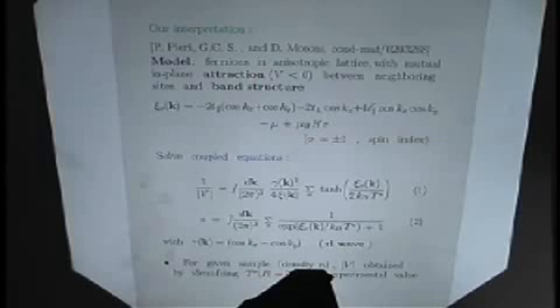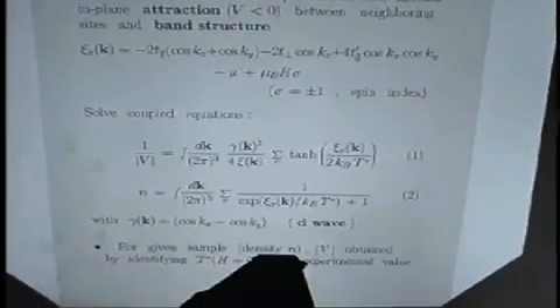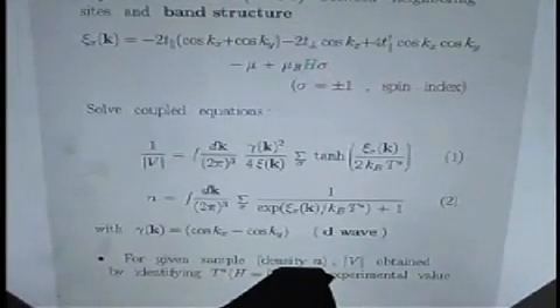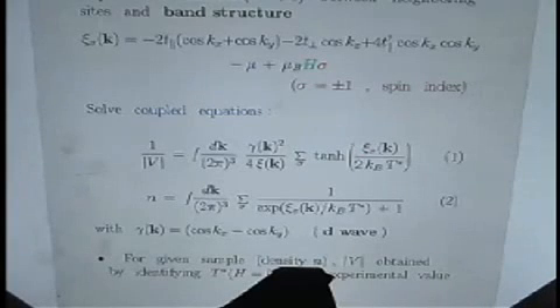The attraction is between electrons in plane, and you get a band structure where you get a hopping matrix element both in plane and out of plane. And of course, you include the effect of the magnetic field on the spin degrees of freedom. You still have two coupled equations to be solved, but now you have two new features, the d-wave symmetry of the gap and the presence of a magnetic field on this spin degrees of freedom here.